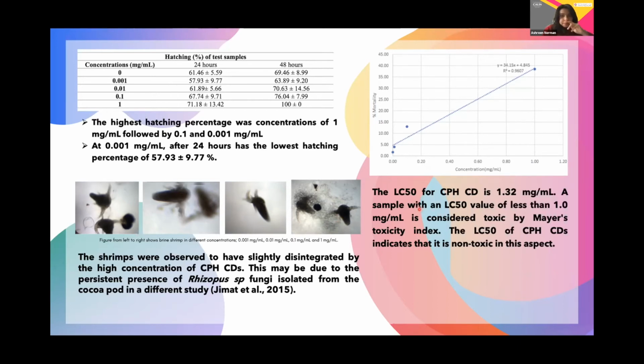For the LC50, according to Mayer's toxicity index, if it is less than 1.0 milligram per ml, then it is toxic. Mine is actually 1.32 milligram per ml, so it shows that it is non-toxic in this aspect.